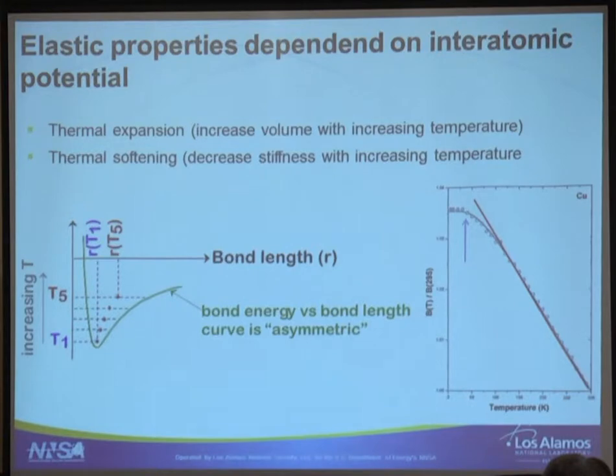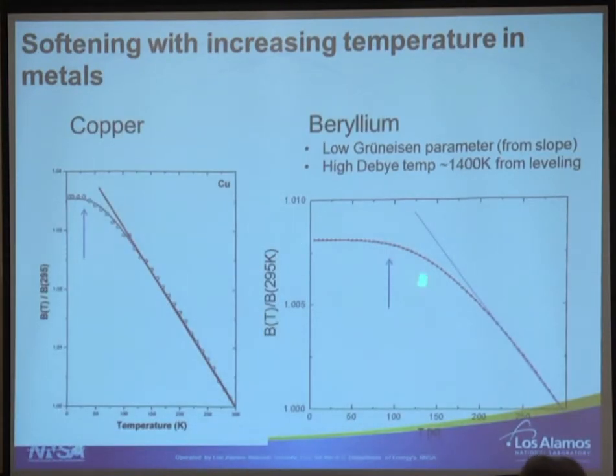So typical bulk modulus as a function of temperature will be flat at low temperature, and then it will decrease linearly at very high temperature. Now, you can go a little bit further and compare two different materials. Both are metals, but the interesting part is that beryllium has a very different type of bonding. It's hexagonal with very close bonding, and then you get very different temperature dependence. This is characteristic of the Debye temperature. The slope is characteristic of the Grüneisen parameter.